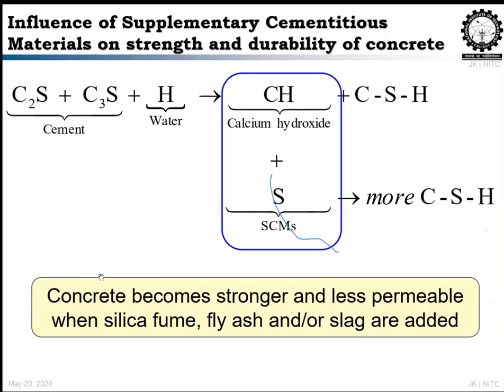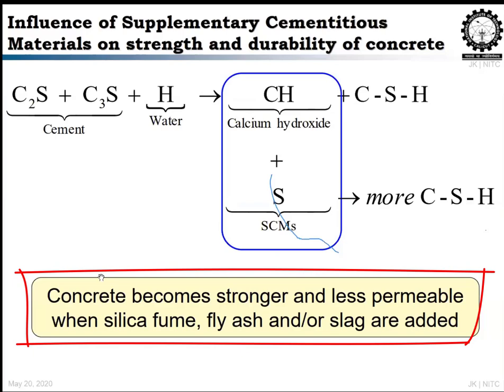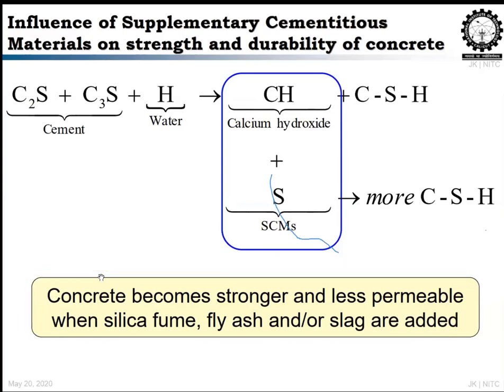And how is this strength achieved just by curing? Again, these secondary cementitious materials which are rich in silica will take the free calcium hydroxide which is there in your cementitious system, which forms when the cement hydrates when reacting with water, and that will form more CSH. CSH is the calcium silicate hydrate, which is the strength giving compound and which makes the concrete very impermeable. So if you have double the CSH, you will get an increase in strength and a very impermeable layer. So use of secondary cementitious materials like silica fume, slag, fly ash is recommended. So we'll see how it influences your durability.